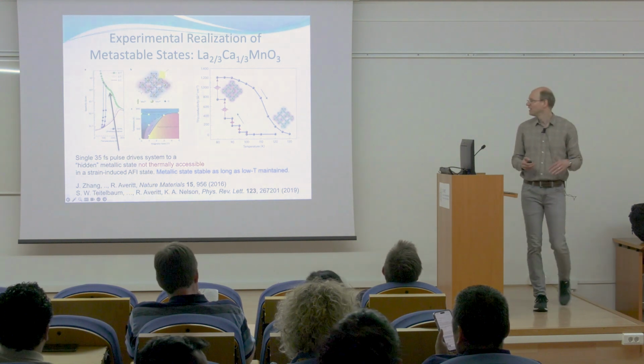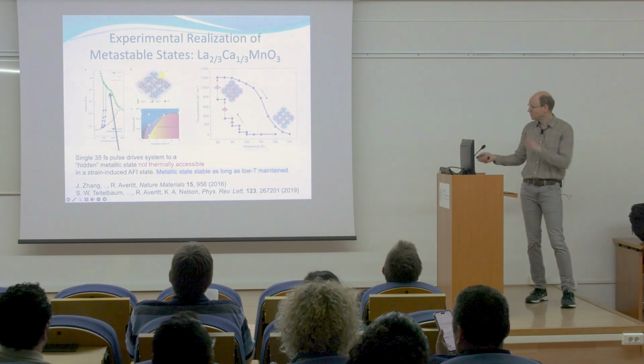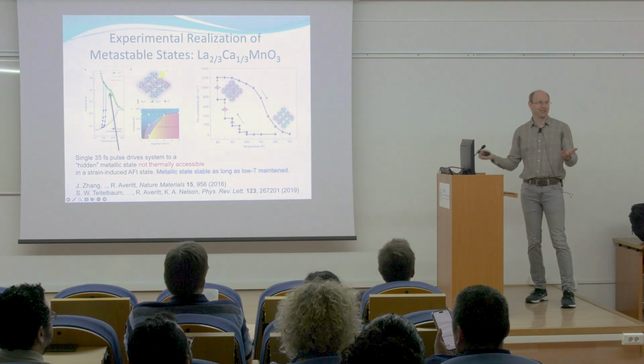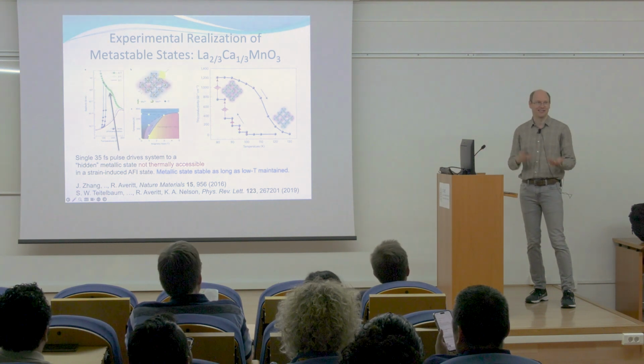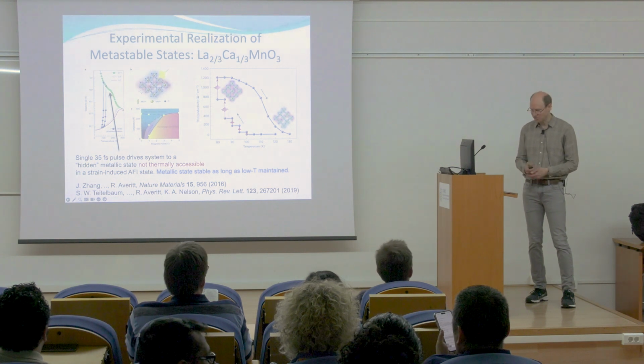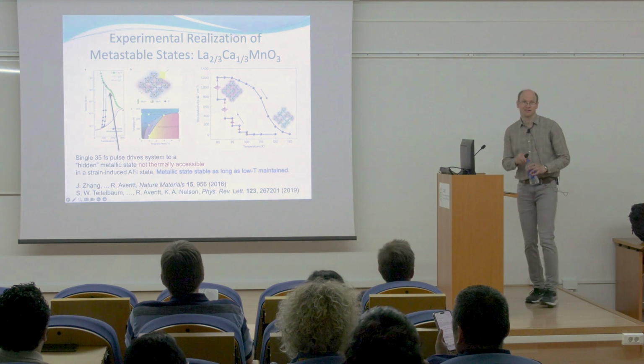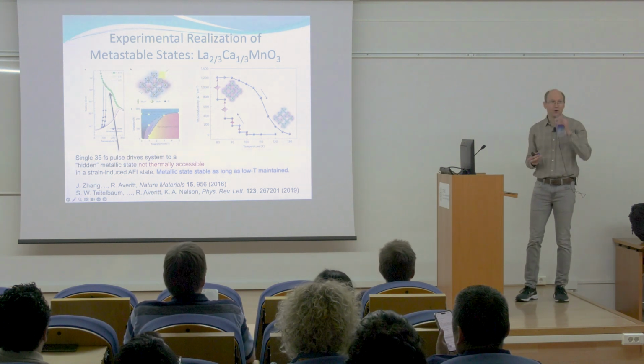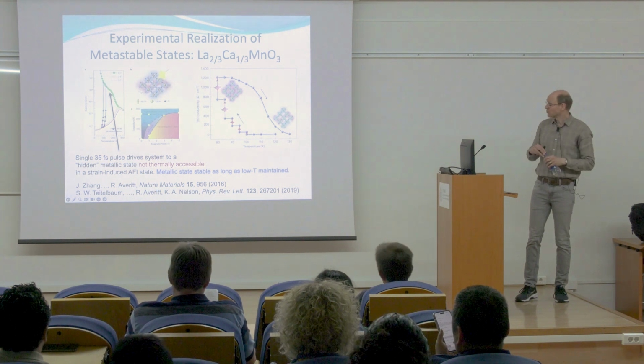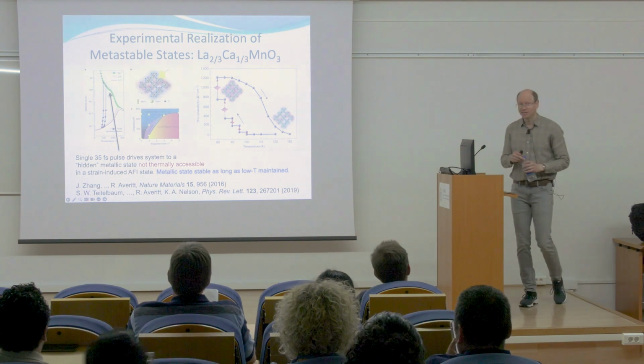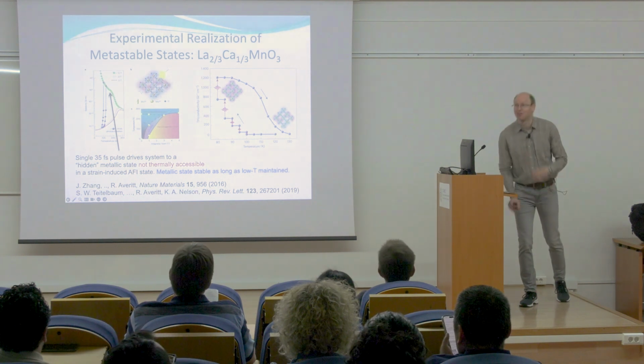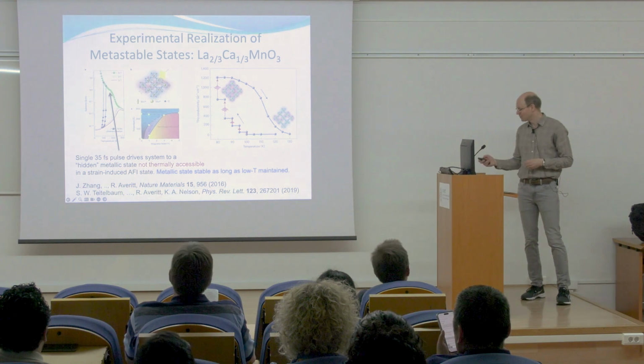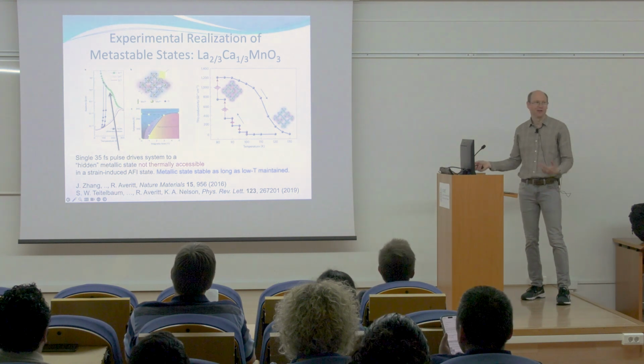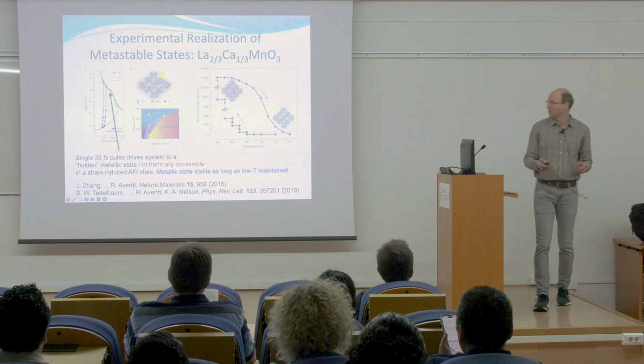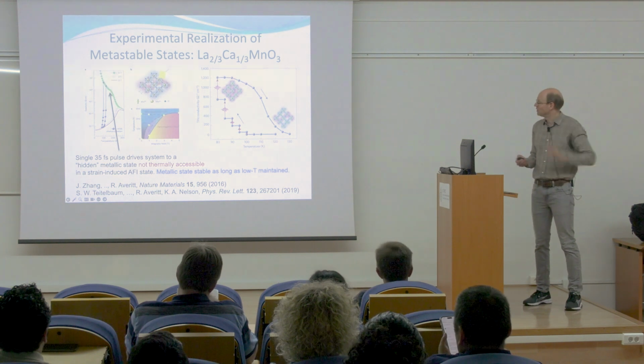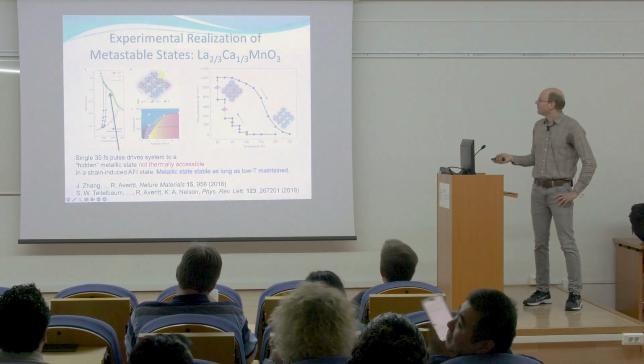So I don't know that that's a cutoff. I talked to the experimentalist who did these experiments, and he said, well, I've only left the sample on the shelf for a few weeks and then gone back and checked it to see that its properties haven't changed. So it might actually have a lifetime which is longer than weeks. But from an engineering perspective, that really opens up a door. Because with weeks, you might be able to make a device for some kind of sensing or whatever it might be. Of course, there's still the temperature issue that it's not room temperature where this occurs, but at lower temperatures. So you might have to keep it cool, but as long as you keep it cool, then it should be OK. So that's the second example.